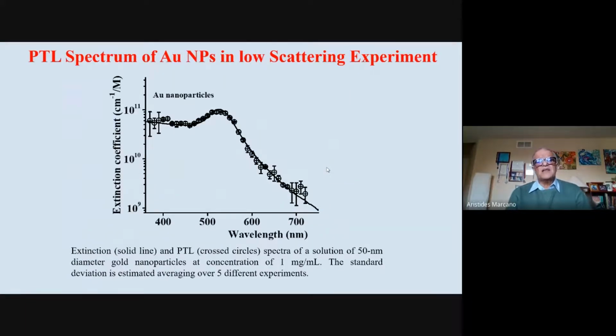This is an experiment we did on gold nanoparticles. They are very popular because of the multitude of applications you can have. And you see these gold nanoparticles actually follow the thermal lensing very, very well, and the absorbance follows the thermal lensing. It means that for these particular nanoparticles, 50 nanometers, the phosphorescence or the fluorescence or the scattering is very small. So it's negligible, and the dominant effect is just the absorption. And the absorption is very big. It means that in these nanoparticles, you can concentrate a lot of energy in a small volume.